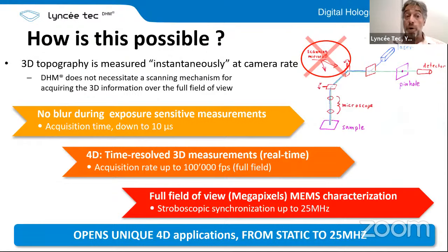First of all, there is no blur during exposure, so it is insensitive to motion. If a sample moves, acquisition time goes down to even 10 microseconds, depending on the laser source we use. Acquisition 4D is possible up to 100,000 frames per second, full frame. And for MEMS we even go to 25 megahertz, but maybe that is a bit less important for inline quality control. So we have many 4D applications from static to 25 megahertz.